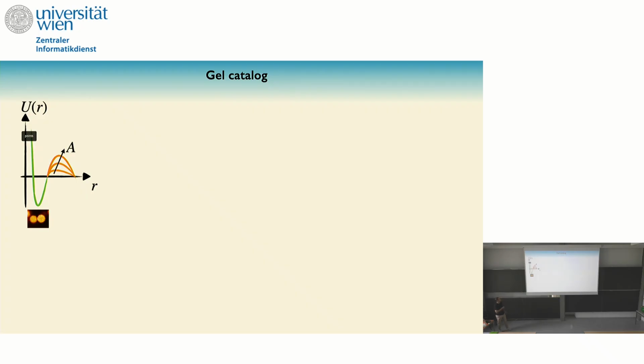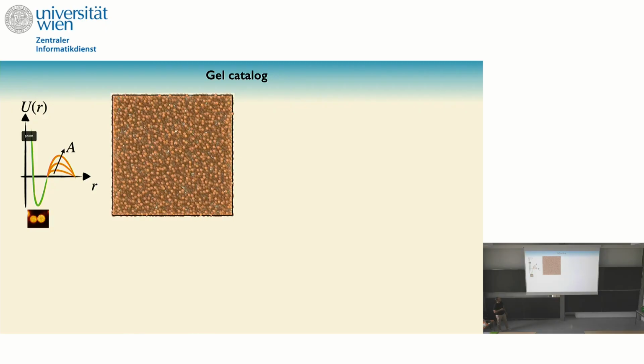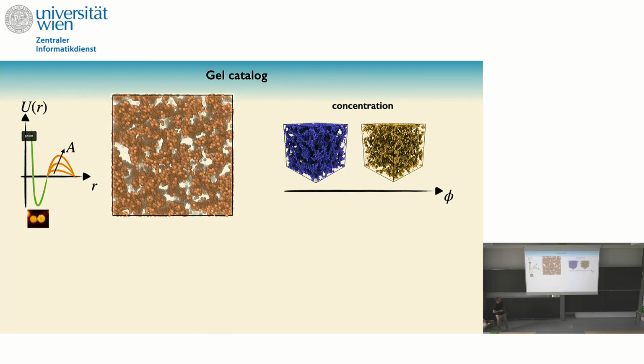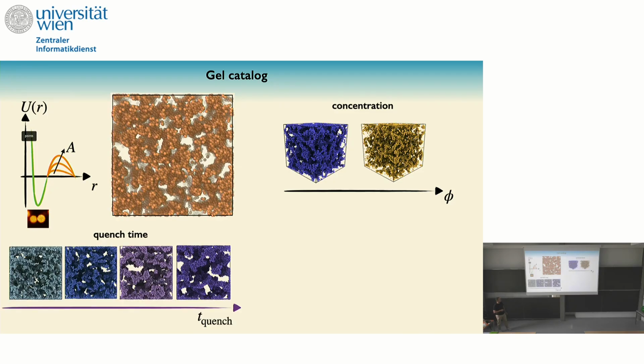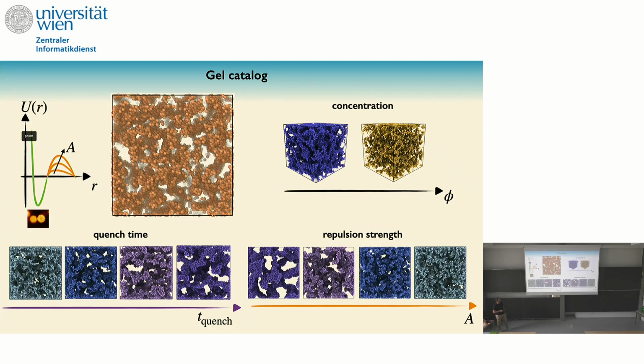So let's start with Lennard-Jones potential. Now let's add, for example, electrostatic interaction and vary those electrostatic interactions. Let's also vary the volume fraction. If you vary the volume fraction, we also get different microstructure. If you vary the way you quench your system, the kinetics of the aggregation process, you would also get a different kind of microstructure. And if you vary the strength of the repulsive interaction that comes from the electrostatic interaction, you would also get different length scales.